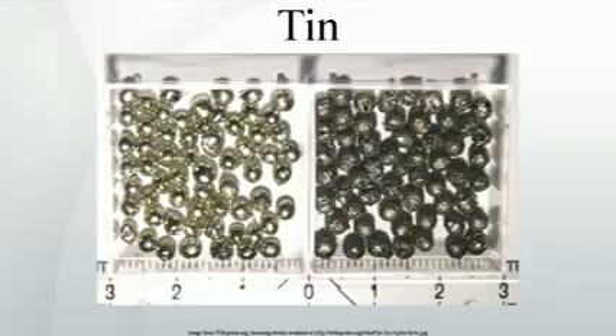Li-ion batteries. Tin forms several intermetallic phases with lithium metal, which makes it a potentially attractive material. Large volumetric expansion of tin upon alloying with lithium and instability of the tin-organic electrolyte interface at low electrochemical potentials are the greatest challenges in employing it in commercial cells.